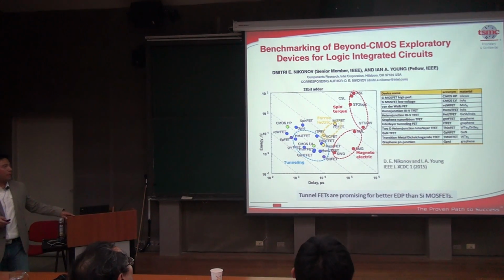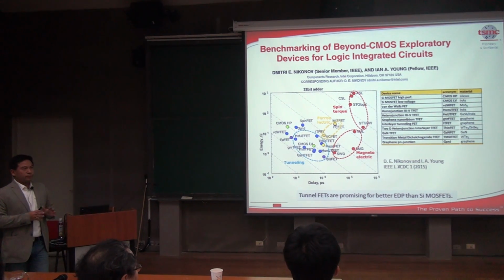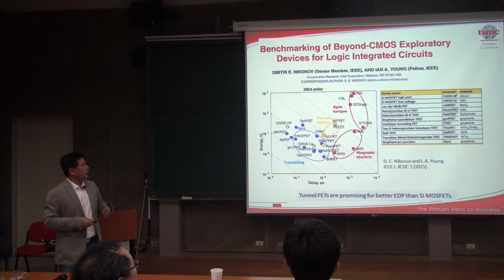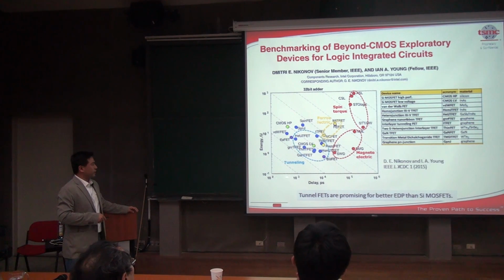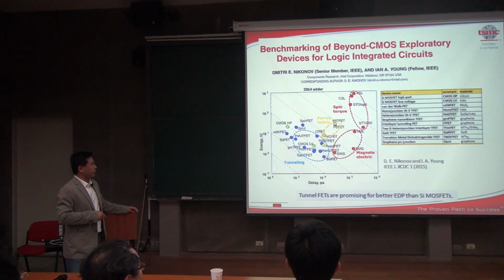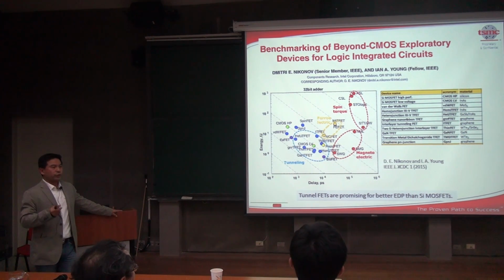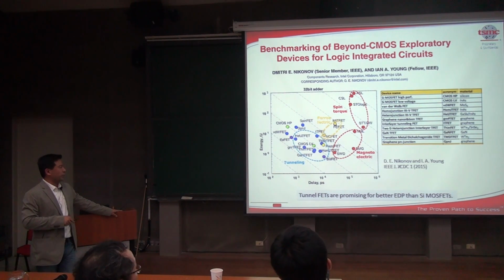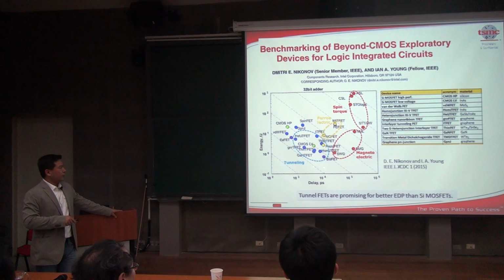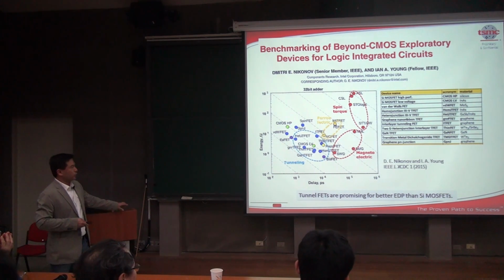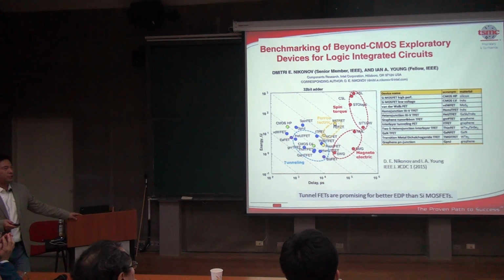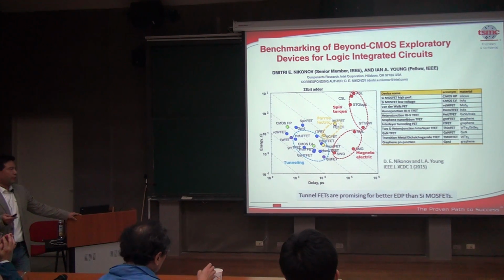So this was a benchmark that was made by Intel earlier this year, where they collect all the possible candidates for future CMOS. And they benchmark in terms of the energy versus delay. Delay is equivalent to speed. So on this chart, the higher speed is smaller delay in this left corner. And this energy is the switching energy for each switching operation for this 32-bit adder. So the smaller the energy, the better. And the CMOS are these two green dots. Tunnel FETs actually scatter around this area, where in some cases they could have a better energy delay product versus silicon. And so that shows that the tunnel FETs combined with 2D could be a very promising candidate for future CMOS enabling low power, higher density operations.